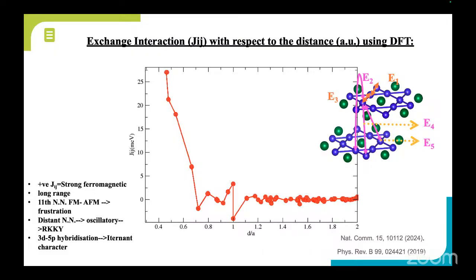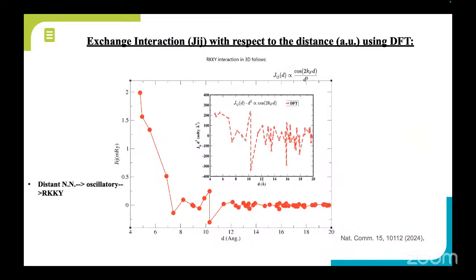To verify whether these RKKY oscillations are there for the distant neighbors, we plotted the Jij scaled with the cube of the distance, which shows that it oscillates with a constant amplitude for the distant neighbors, following the three-dimensional behavior. But having said that, a more quantitative theory of whether it follows RKKY needs further investigation in terms of finding the wave vector for the Fermi surface.